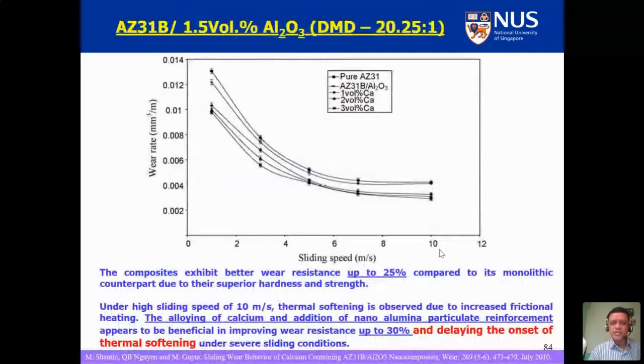Another application of metal-based material is in sliding applications. Remember the tracks, remember the wheels, remember the reciprocating moving objects and all these things. So we did some work in collaboration with my colleague who is a tribological expert. And you can see, just by putting 1.5% of aluminum oxide, we get a 25% improvement in the wear resistance of the material. You can further increase it if you put additional calcium in there, up to 3%. Now you get 50% improvement overall by putting Al2O3 and calcium.